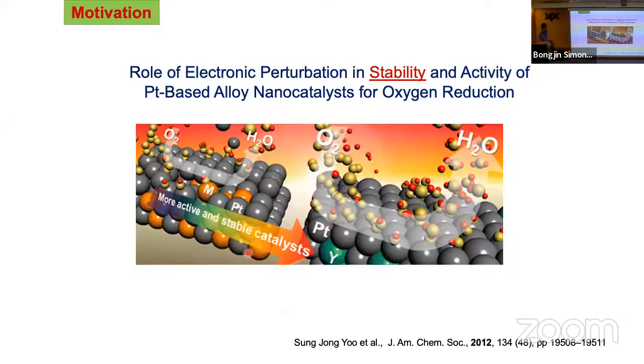The problem is, when you make these platinum alloys like this, many people tried it, but they ran into the so-called stability issue. In other words, this transition metal that was sitting below actually started leaching out because of the reaction. This oxygen starts to push this transition metal to the surface, and that ruins the whole performance. So in the first few cycles it works really well, but after a few cycles it starts to deteriorate, and then the surface is no longer valid. So this was coming out between 2007 and 2012. Many people followed up on the idea, ran this measurement, and ran into the similar issue.